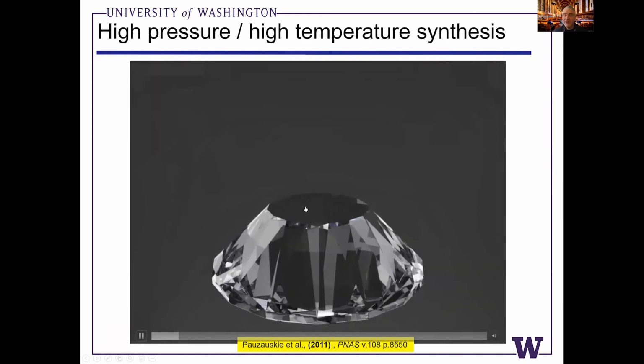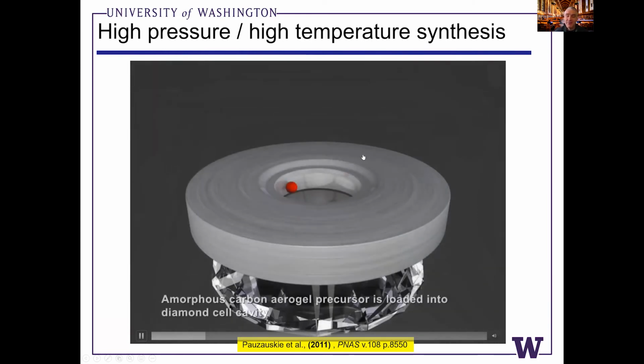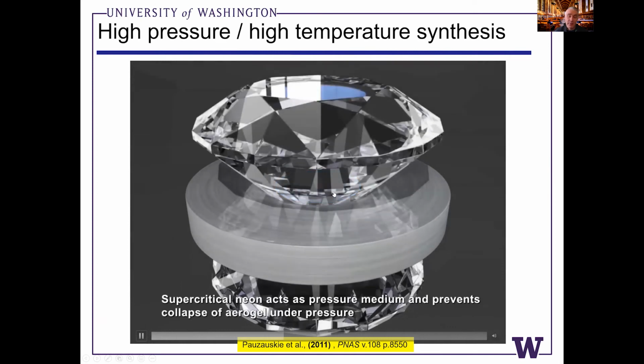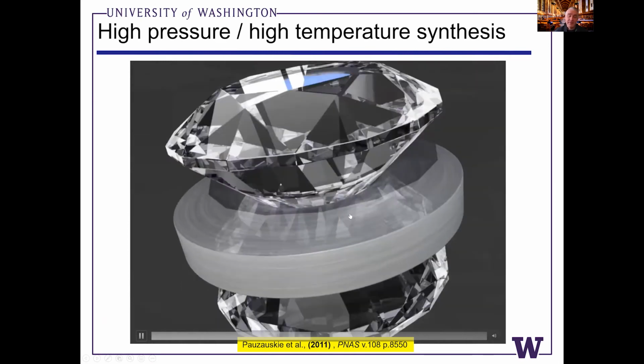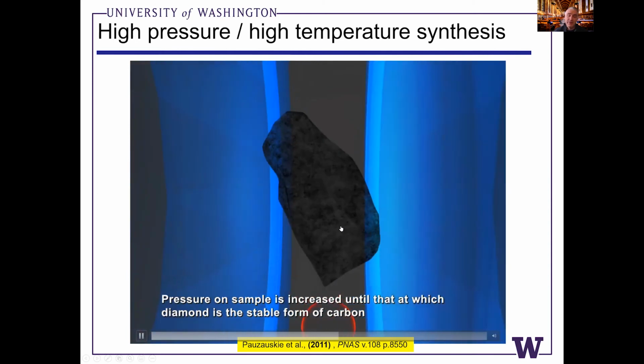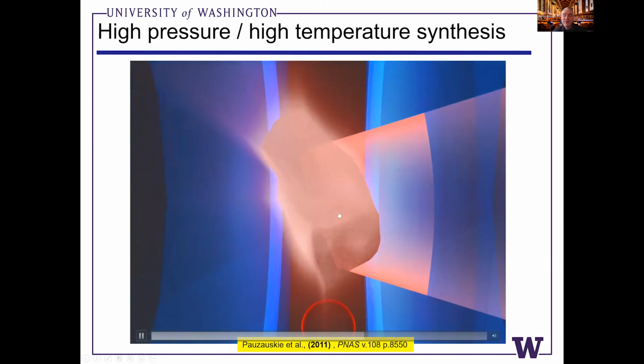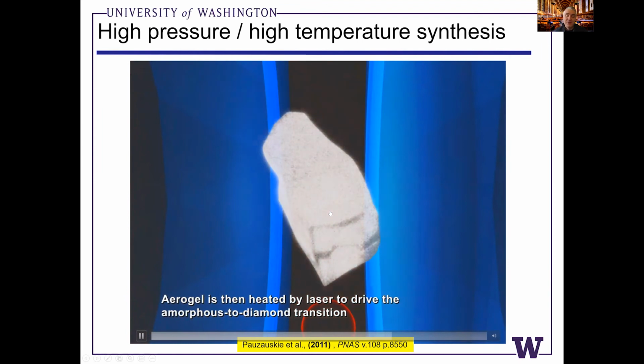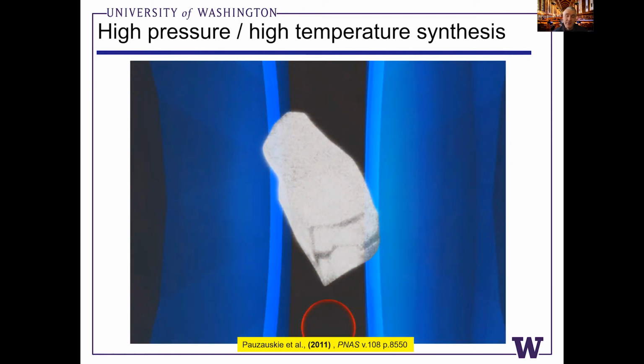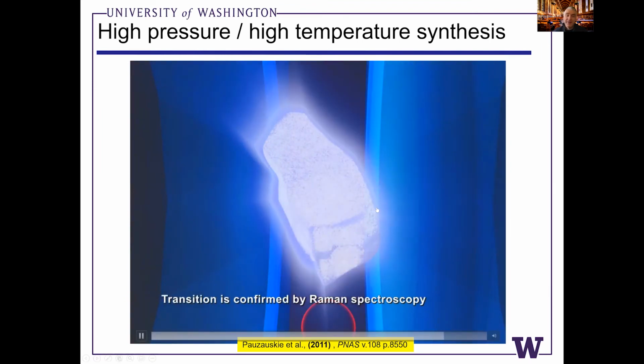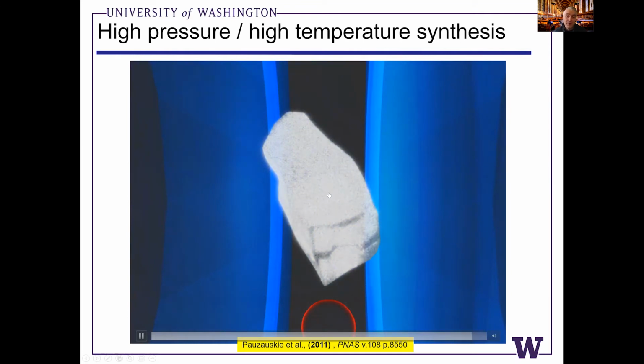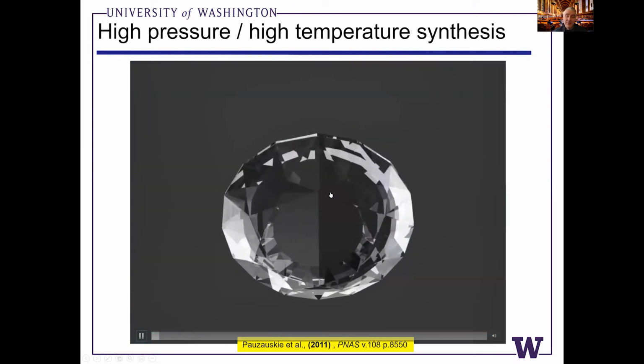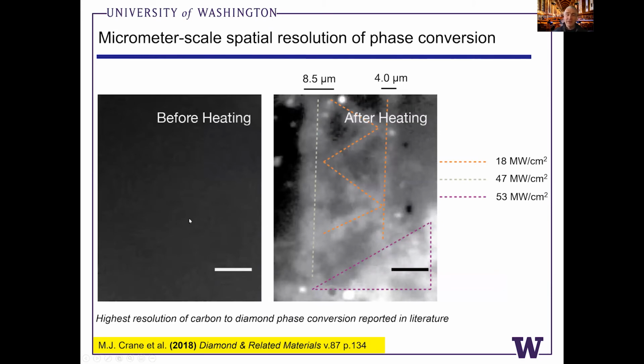So here's a cartoon sort of schematic of the process. We've got the diamond anvil itself. We've got a ruby crystal, the amorphous carbon aerogel that we fill with chemically inert noble gas. We squeeze this system to an arbitrary pressure of interest, and then we use laser heating to heat the amorphous carbon and drive a phase transition to diamond from amorphous carbon. We can then follow up with a second laser and look for Raman spectra or photoluminescence within the diamond anvil cell itself.